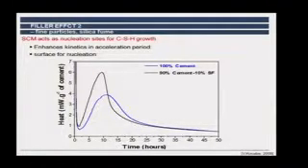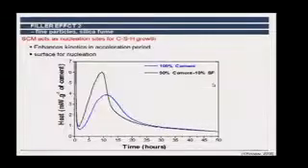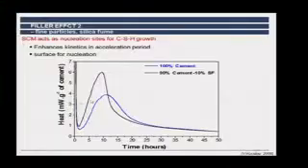Now, if you've got a very, very fine particle, like if you've got this silica fume, which has this size of about 1/10 of a micron, we know silica fume is reactive, but even though it's quite reactive, there's almost minimal reaction in the first day. In the first day, the action of silica fume is mainly to greatly enhance the reaction of the cement.